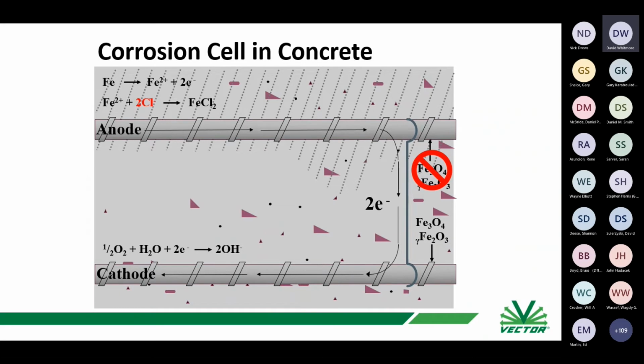And these electrons that have flowed down here to this area that has no chlorides, they're going to react and form more hydroxyl ions, which, if you remember back to your high school chemistry, is how you measure pH or alkalinity, right? So you're actually generating additional alkalinity at the cathode where the electrons are flowing to. Okay, and this steel down here is being protected. So a cathode is an electrode which is receiving electrons. And because it's receiving electrons, it is by definition protected and it cannot be corroding.